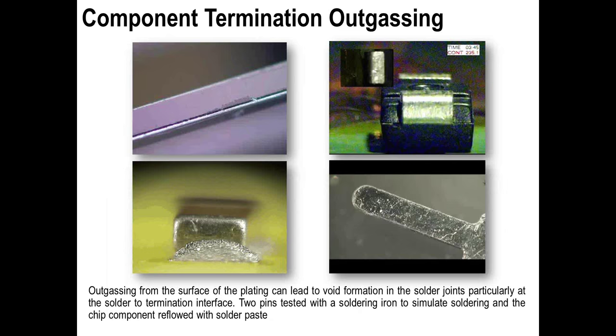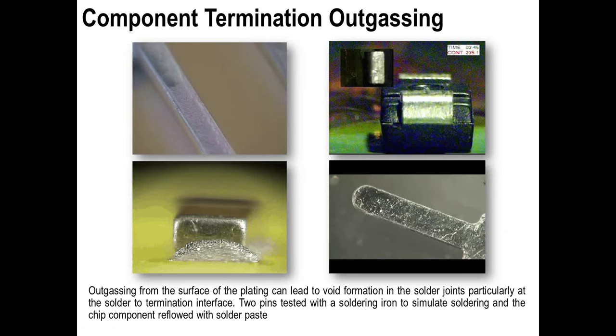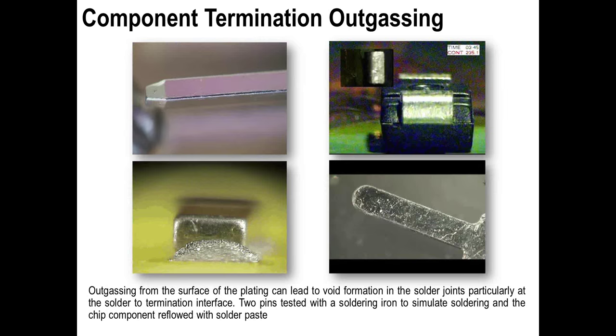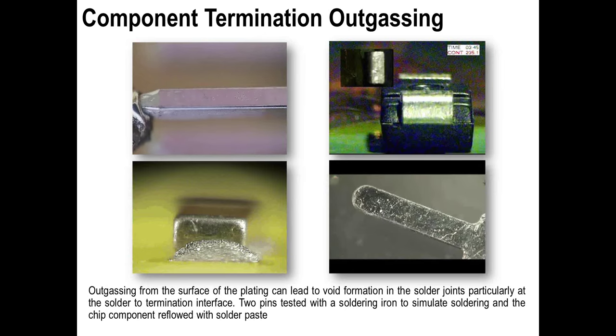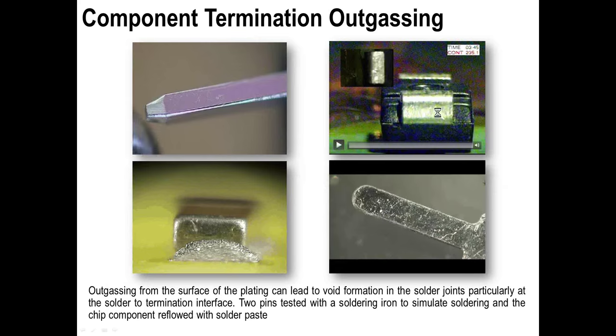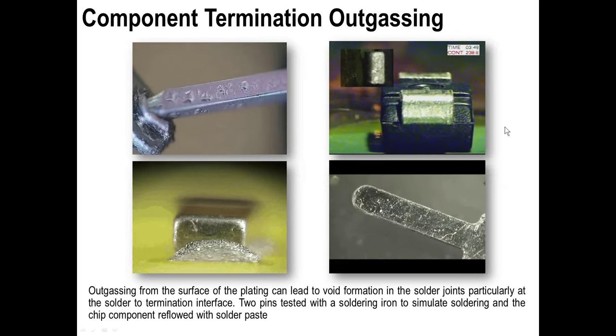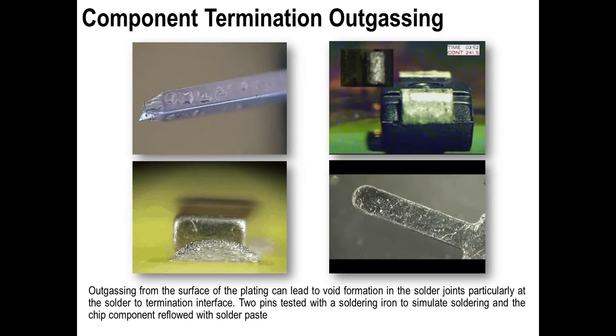Now, the other reason that we see voids, and please consider this when you're looking at solving problems, is the actual materials that you're soldering to themselves. On the top left, I'm showing you a video clip which shows outgassing from the surface of the plating as I simulate the soldering operation. You can see the gassing visible on the surface of the plating. This is a pin on a connector, and this generated hundreds of thousands of small micro voids. This example top right, you're seeing reflow soldering of an electrolytic capacitor, and you can see the plating gassing on the surface of the termination. Now remember, there's no solder paste here at all. This is just the termination. So don't always believe it's a solder paste and the profile, which is the issue, also look at the component.